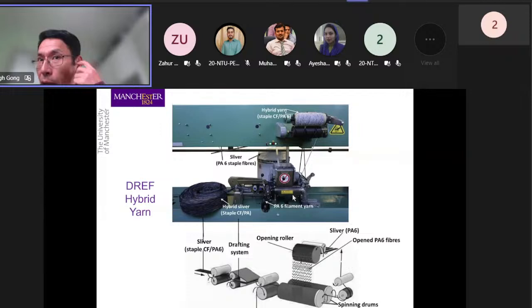And this is somebody else's work. This is by Hassan, I think. Again, this is published in 2018. You can see here they are using a Dref machine, but again, they are using a mixing of staple fiber, carbon fibers, and also nylon. As I said earlier, drafting of pure carbon fibers is difficult to control, so they use the nylon to assist that. And then they use another nylon staple fiber coming from the top. And then they also fed another nylon filament through the center. So you can see a lot of nylon fibers involved in actually making the eventual yarn, just because pure carbon fibers are hard to handle.